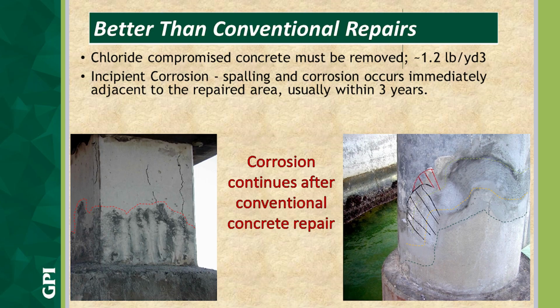Incipient corrosion, also commonly called halo effect, is what's depicted in these pictures. On the left, you can see a concrete repair, and you can see the spalling extending vertically up beyond the repair. On the right, you can see at least three repairs. You've got the green, the yellow, and it looks like black. And the owner here is chasing it. They do the first repair. The corrosion begins in the second area right adjacent to the first repair. They come back and fix that. Well, now we've got corrosion occurring in the next section just adjacent to it again.